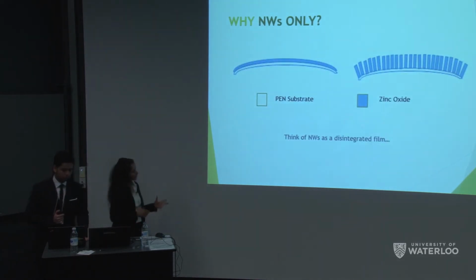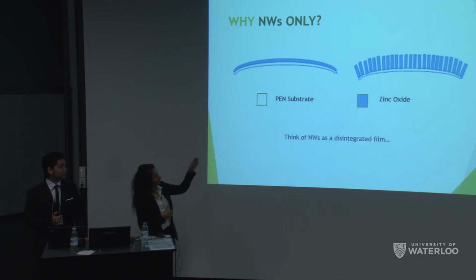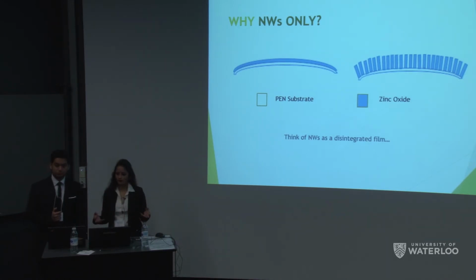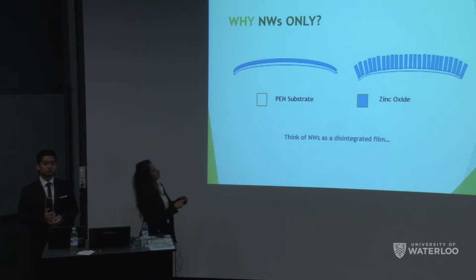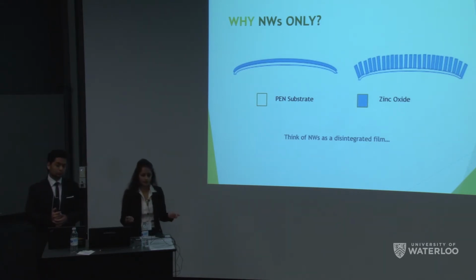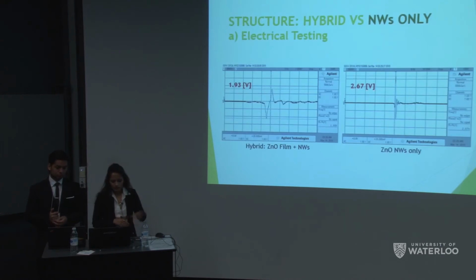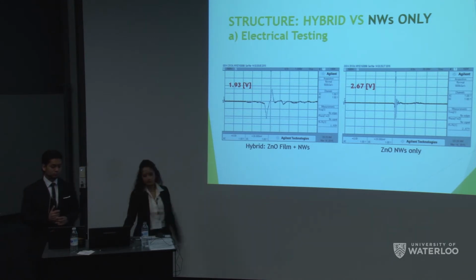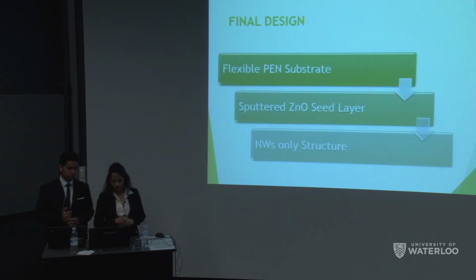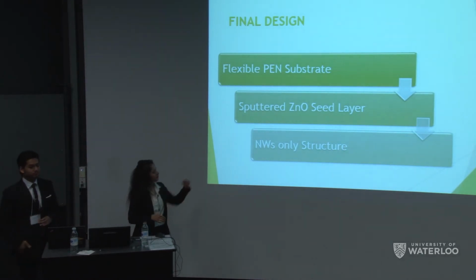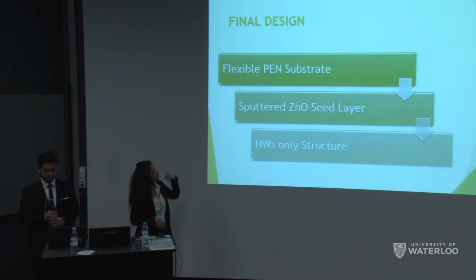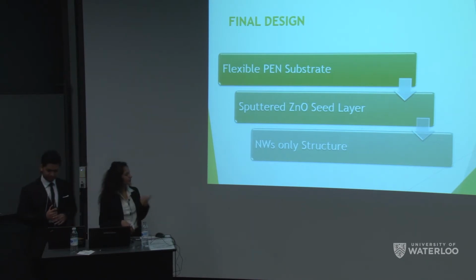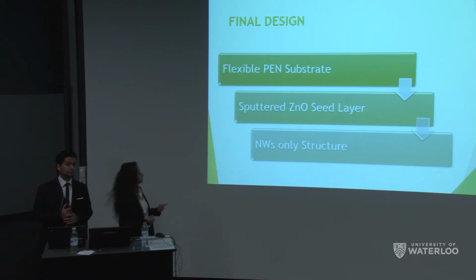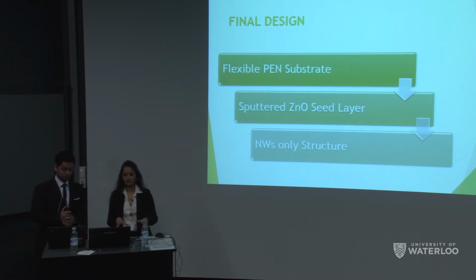So why nanowires only and not the bulk zinc oxide film? Well, we can think of nanowires as basically a disintegrated zinc oxide film, which we propose would provide more flexibility and durability to the device. So again, even here we saw numbers, and definitely the nanowires only device was a clear winner. So just to summarize all the design considerations and what we ended up optimizing, we used a flexible PEN substrate, we used a sputtered zinc oxide seed layer for growing the nanowires, and we used the nanowires only structure.